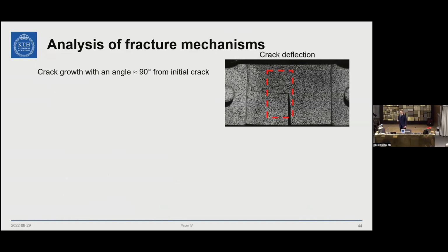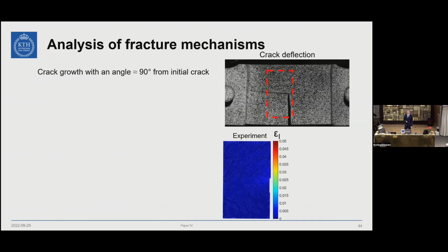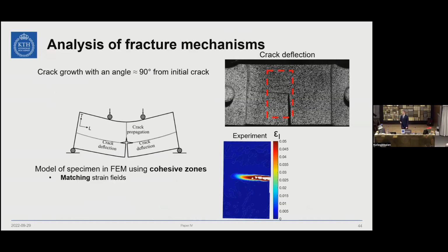We can use strain field measurements to investigate what's actually going on in the strain field. We can see then at the crack tip, tensile strains are building up, promoting the crack to deflect along the fiber direction. In order for us to understand what's going on around the crack, we can postulate cohesive zone models in the direction where we know that the crack is propagating from experiments, but also in the direction from where we want the crack to grow. And then we can match those fields together.